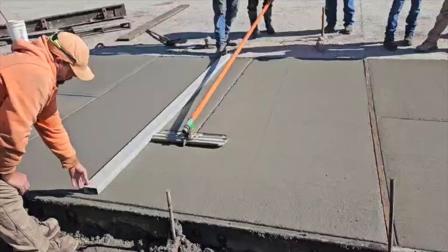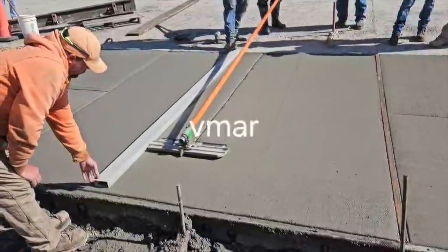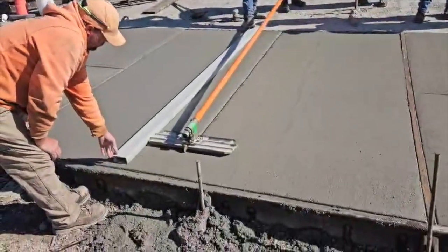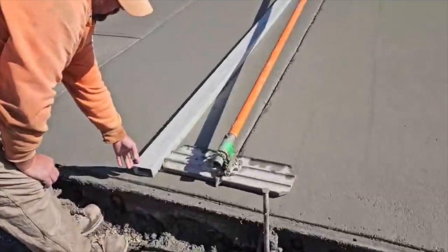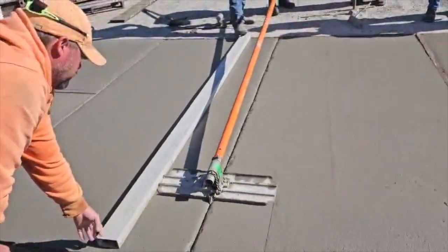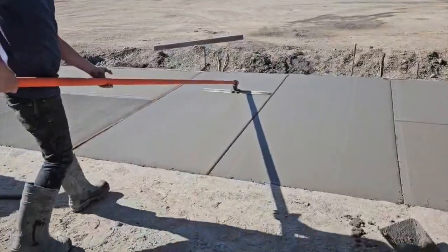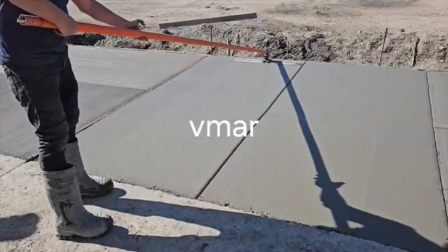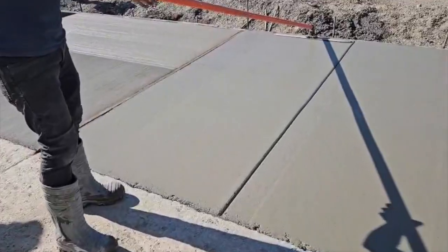The third test we did, we used VMAR F100 added to the mix. VMAR is a viscosity modifier. We put it in right before loading the truck, poured it right on the sand. The result was about a 4.25 inch slump.